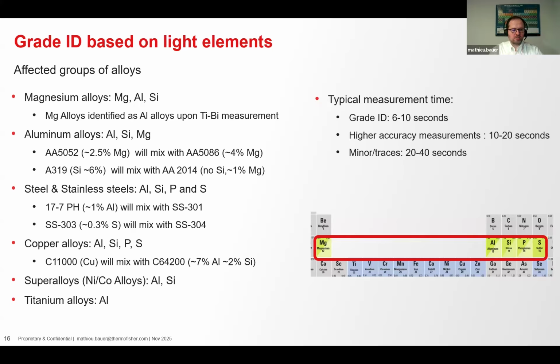That's also the case for stainless steel 303 that contains 0.3% sulfur versus 304 that doesn't contain sulfur but has the exact same composition for the other alloying elements. Also, most copper alloys can be identified without light elements. Few exceptions are, for example, pure copper that differs from the aluminum bronze C642 only upon the aluminum and silicon content. Therefore, we don't really need to measure the difference because pure copper is red while the aluminum bronze is yellowish, so they can also be differentiated not only via the chemistry but also via their aspects.